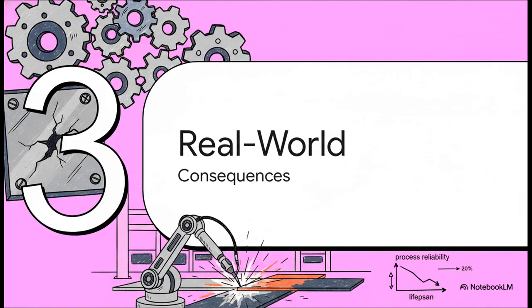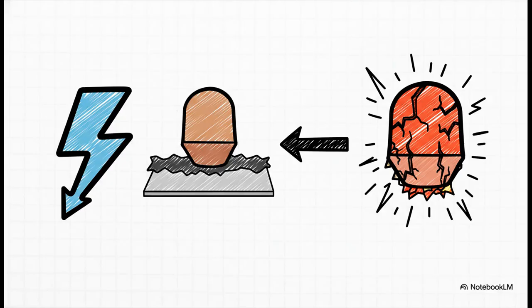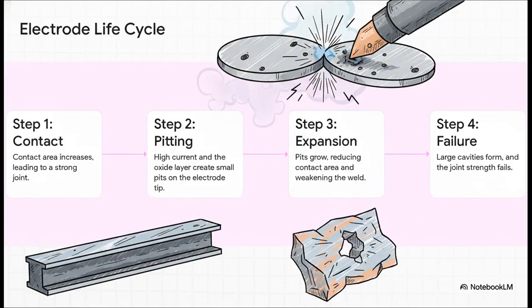Now, these metallurgical challenges aren't just something for a textbook. They have serious, practical consequences out on the factory floor, affecting everything from how reliable the process is to the lifespan of the equipment itself. So here's the crucial point. To overcome aluminum's low resistance, you have to use a massive amount of current. But that current has to pass through the highly resistive oxide layer on the surface. And this creates this intense, localized heat right at the point of contact, which is just brutal on the copper electrodes. This 4-stage cycle shows you exactly what happens.